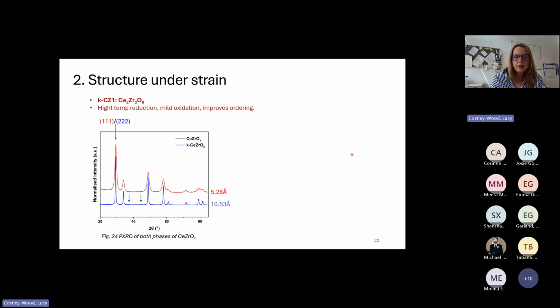So this is the exact same material, 50-50 cerium zirconium with oxygen, but it's gone through a high temperature redox treatment, which improves the ordering and doubles the unit cell size, which you can see here. What this change does then is, in our ceria zirconia material I was just talking about before, we have domains of ceria-rich material and domains of zirconia-rich material linked by these oxygens at the interface, and these are the ones that it's believed are removed. But after this treatment to form the kappa phase, we alternate exactly cerium, zirconium, cerium, zirconium, and that massively improves our oxygen storage capacity.